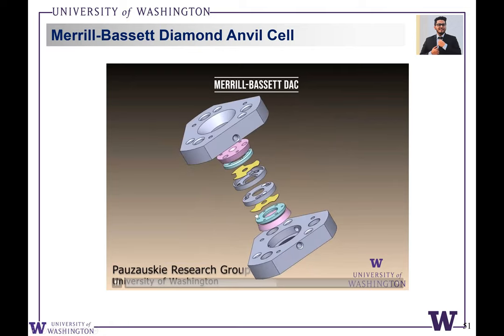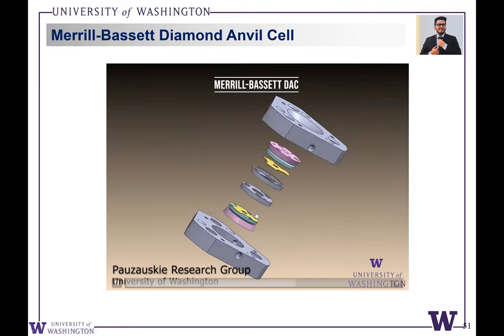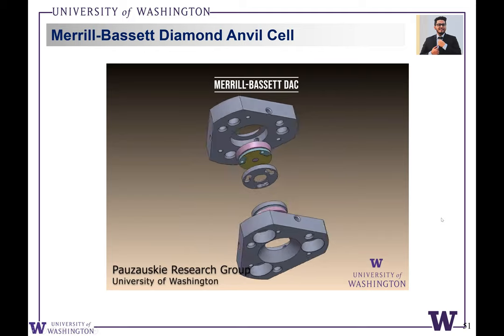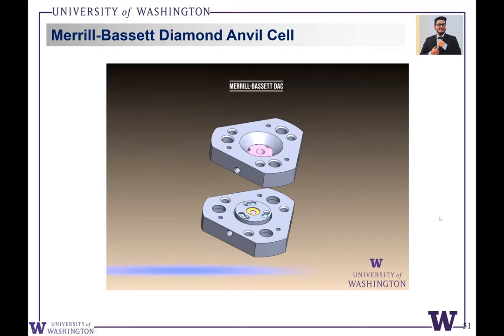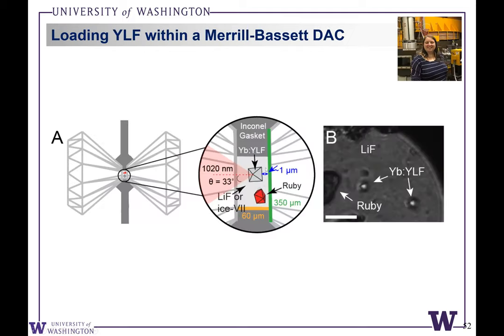We basically have our standard Merrill Bassett diamond anvil cell, nothing fancy. We have two anvils that we then load the YLF crystal between the anvils. This is a lithium fluoride pressure medium. We've also done experiments more recently in ice VII, just squeezing water and freezing water. You can see the optical micrograph of the diamonds, or I'm sorry, the yttrium lithium fluoride crystals here, the sort of pressure medium here. This is lithium fluoride in this experiment. We also have ruby crystals adjacent to do pressure sensing.